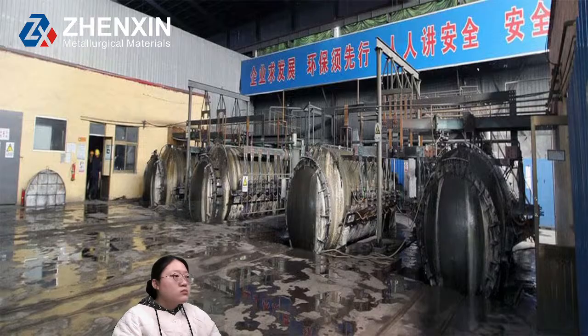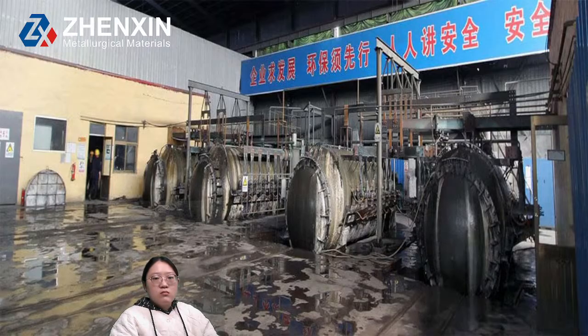If your sulfur is high, section is thick, casting geometry is complex, when you face this situation, just choose the rare earth ferrosilicon magnesium, the rare earth nodulizer.